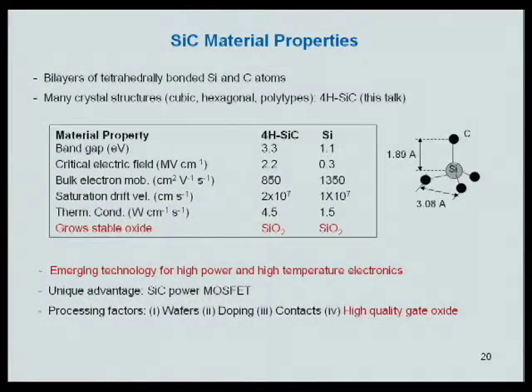Let's look at the difference between the materials. What you see is that the silicon band gap is about 1 electron volt. The silicon carbide band gap is about 3 times larger. The critical electric field is significantly larger for silicon carbide than for silicon. Other properties are quite similar. There's a little bit of difference in electron mobility and saturation velocity.